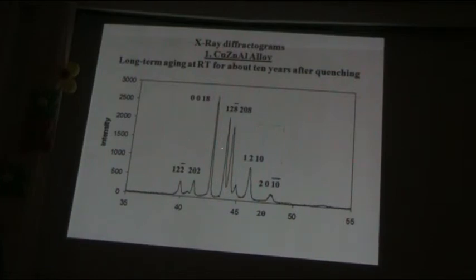This is an X-ray diffractogram of a copper-zinc-aluminium alloy sample. It exhibits that this sample has the ordered structures in the martensitic condition, and these peaks have great importance in the examination of the martensitic transformation. In particular, these phases have great importance.